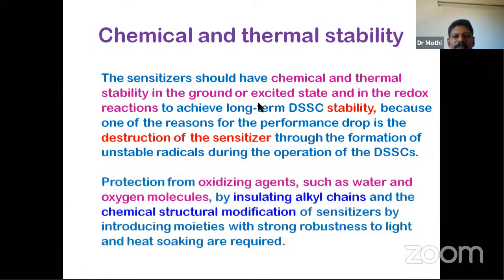As everyone must have seen, most of our clothes are dyed using organic dyes. So if we leave these clothes in open sunlight for a long time, we would have seen a fading of the color. What happened during this process is the dye molecule is deteriorated or destroyed by the sunlight. Okay, the free radicals that are produced destroy the dye molecule. So this happens in the DSSC dye as well, but it should be designed in such a way that this should be avoided or minimized. Okay. So this helps in long-term stability, and then it should be protected from oxidizing agents such as water and oxygen molecules. As I already told, long alkyl chains and structural modifications are useful for doing this job.